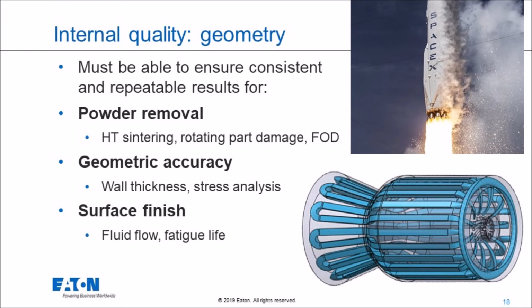So first things first, how do you remove the powder and how do you ensure that the powder is fully removed? If you take a part with powder still left on the walls and put it through a heat treat cycle, that powder can sinter to the walls, and now you have risk of FOD, foreign object debris, flying off into your fuel line and causing damage to the part. And aerospace companies take this extremely seriously.